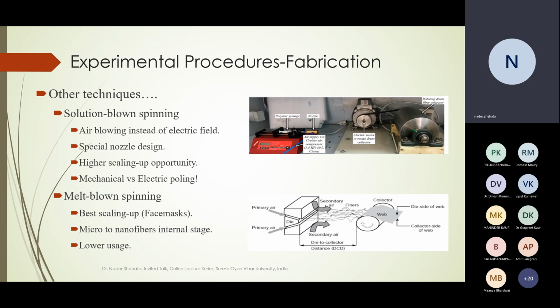There are other techniques to generate nanofibers like PVDF nanofibers, which do not depend on the electric field. Like the first photo here, related to solution blown spinning, which depends on relatively high pressure of air blowing, which could affect the polymer jet, and consequently it can form nanofibers, but replacing the traditional contribution of the electric field. This technique is more convenient compared to electrospinning because of the opportunity of higher scaling up.